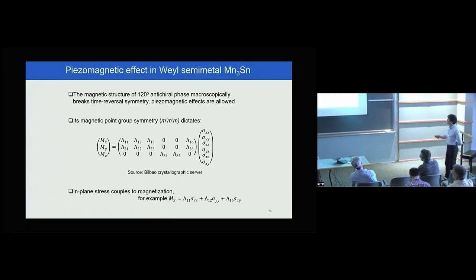states. So let's see how this works for the Weyl metals. Manganese tin. This material, of course, exhibits the anomalous Hall effect, time reversal symmetry is broken, and it should be allowed. And there is a linear coefficient, which actually has become simplified because of the magnetic point group symmetry. For example, if you take the in-plane magnetization, it should be linear with the sigma xx, sigma yy, sigma xy. Okay.